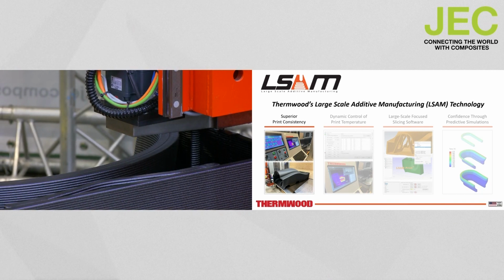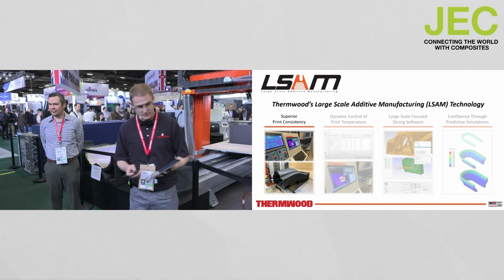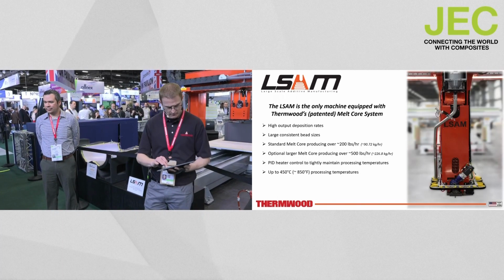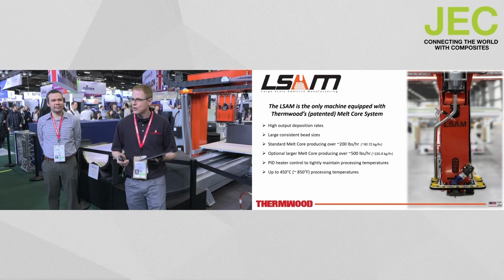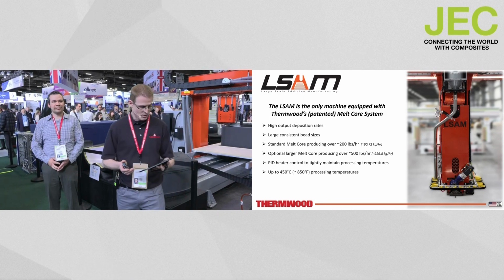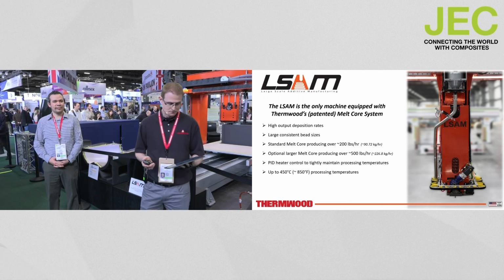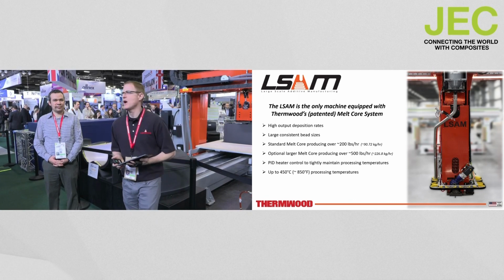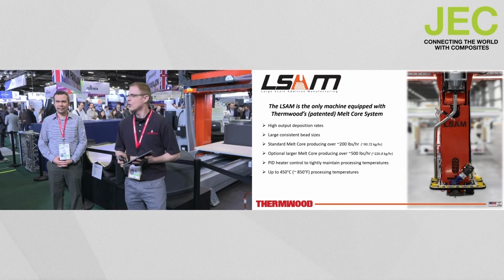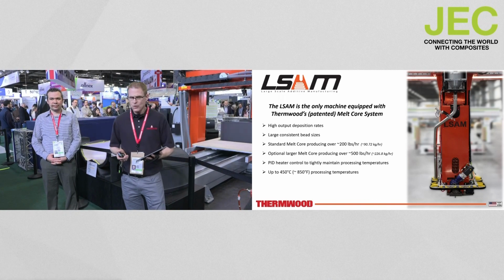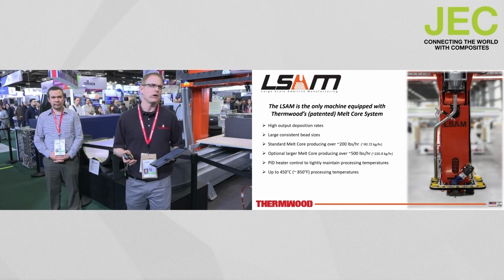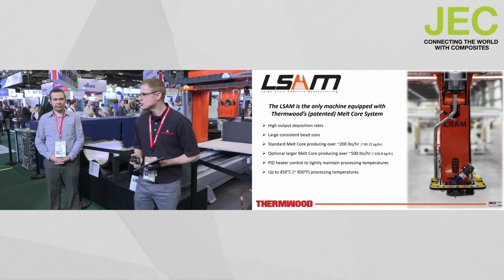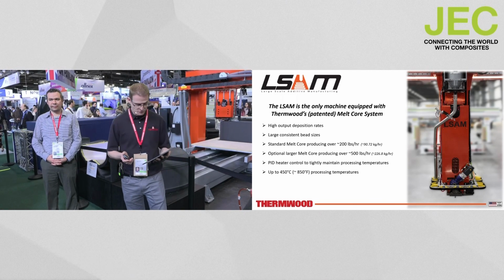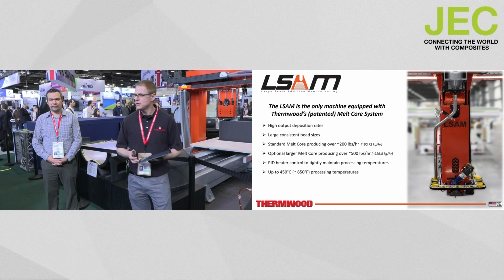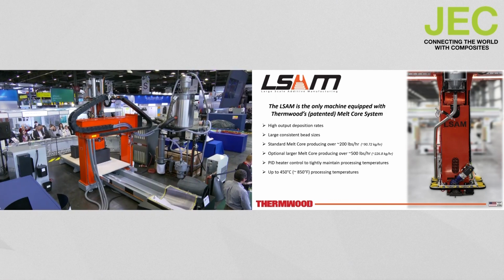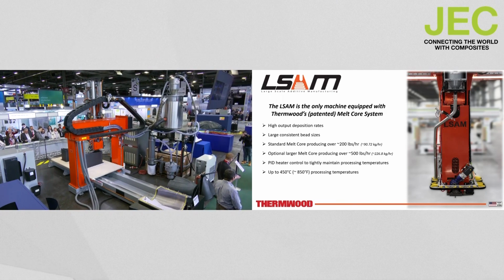So let's explore how the LSAM produces superior print consistency. First, the LSAM is the only machine equipped with Thermwood's patented melt core system for processing materials. The melt core is designed for high output deposition rates to produce large, consistent bead sizes. With our standard melt core producing over 200 pounds an hour and our optional larger core producing over 500 pounds per hour. It uses PID heater control to precisely maintain temperatures up to 450 C.